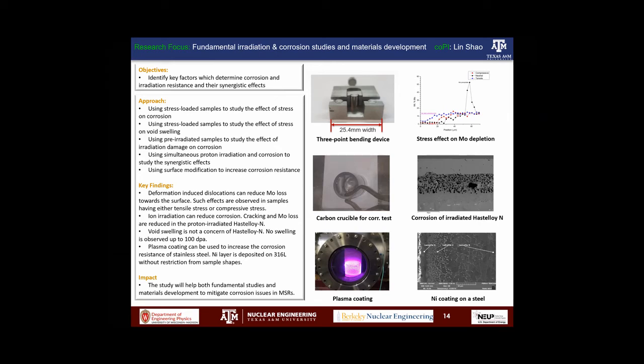This dislocation not only changed the mechanical property of the materials, but also caused complicated elemental segregation. The sample after corrosion shows cavity formation and chromium precipitation. And the third task that is also quite interesting is basically a surface modification or a coating. So we applied the nickel layer on top of 316 steel to study the corrosion resistance after the material has been coated.